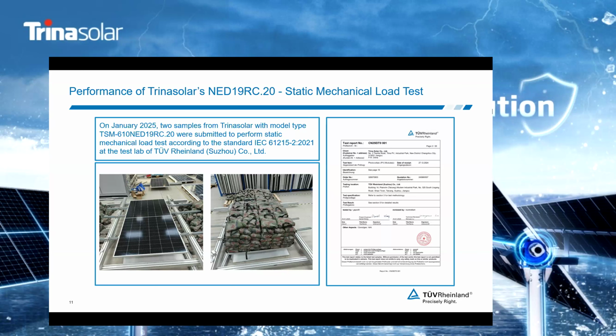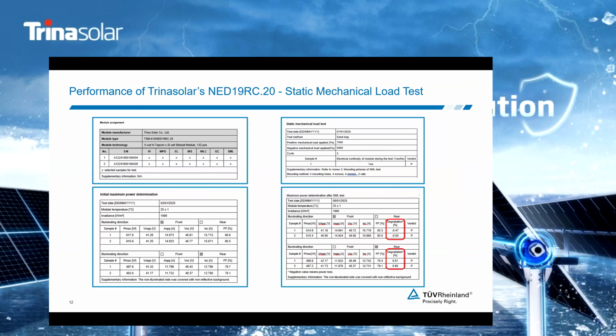The test requires at least three cycles. One cycle consists of an hour on the front side and another hour on the rear side, so the total test duration is 6 hours. For the two samples, we also need the visual inspection, maximum power determination, EL images, insulation test, wet leakage current test, and grounding continuity test, but what we care about is the static mechanical load test. We tested two samples. The first sample was tested at 7,000 Pascal on the front side and 5,000 at the rear side, which is much larger than the minimum requirement of the standard, positive and negative both 2,400 Pascal.